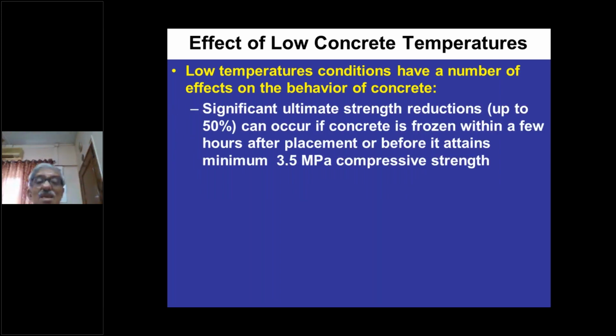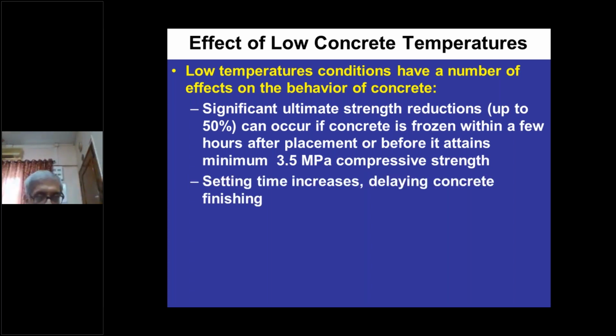Effect of low temperature. Significant drop in strength can occur if the water inside the concrete freezes. So you must remember that the minimum strength of concrete, 3.5 megapascal compressive strength, should be achieved within a few hours of concreting. Otherwise, the water inside the concrete will start freezing and cause enormous drop in strength. Setting time increases,